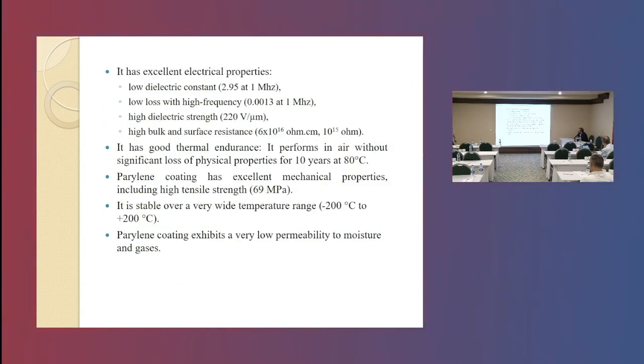It has excellent electrical properties such as low dielectric constant, low loss with high frequency, high dielectric strength, and high bulk and surface resistance. It has good thermal endurance and has mechanical properties. It is stable over a very wide temperature range from minus 200 Celsius to plus 200 Celsius.